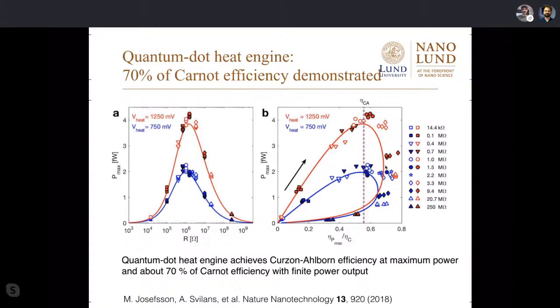So this is basically what we had set out to do. We wanted to show that with a quantum dot, it's indeed possible to convert heat into electricity. And it's important that I emphasize that for the electronic system, we are totally ignoring the fact that there are also phonons. But for the electronic system, we can indeed, even in practice, convert heat into electricity with finite power output at 70% or maybe even a bit above of Carnot efficiency, which is as good as, or I would say in most cases better than, macroscopic optimized heat engines perform. So that was very nice.